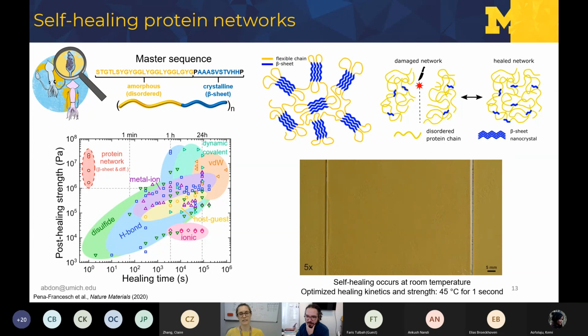This is a matter of kinetics, right? If you remember in here, we can get very fast healing by applying a little bit of heat, just above room temperature, right? 40 degrees is not too bad, right? So what happens is the healing at room temperature happens over a longer period of time, so we can just selectively heat the damaged area and not heat up the rest. So we can have a heterogeneous heating and healing of the structure. If you put everything in an oven, for example, then you will get a blob, and those two membranes will stick together.